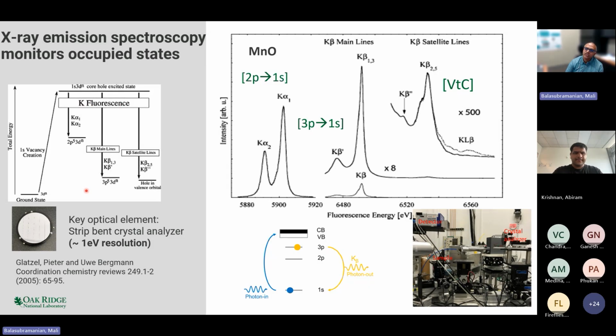And when you have fluorescence emissions, what happens is that an electron from a 2p level might fall back and fill up this hole that you have created here. Or you might have an electron fall from the 3p level into this core state, or you could have an electron that comes from the valence orbitals or the occupied states in the valence region into these holes. So all of these things produce emission spectra, which by using crystal analyzers, one can energy analyze.